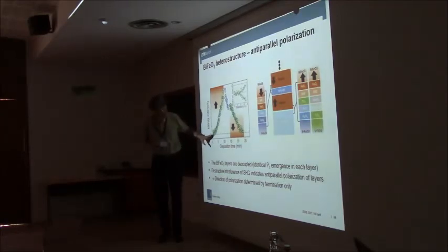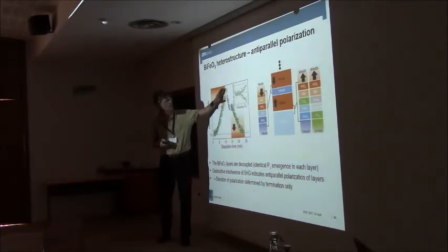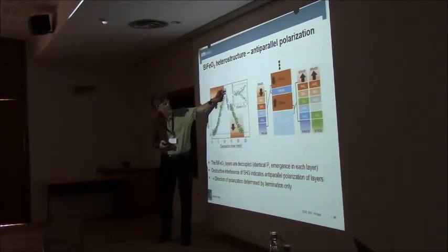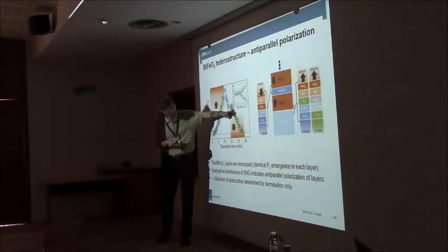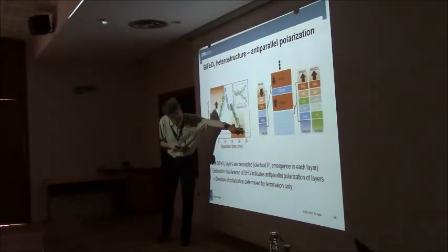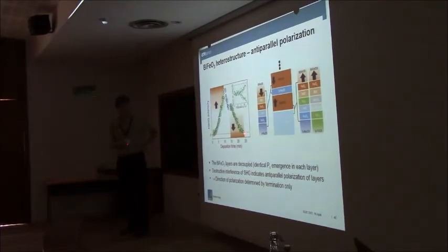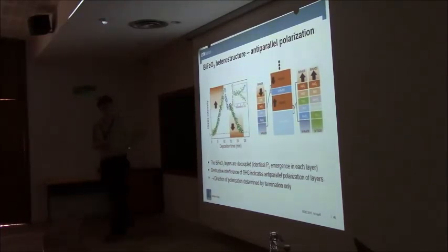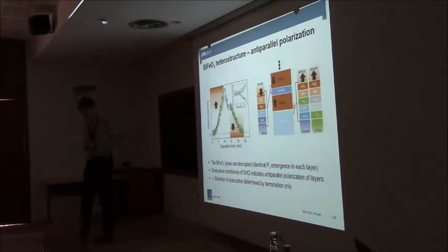You can see it when you track the growth by second harmonic generation. In the first layer you have this continuous increase. Then you grow your metallic interlayer that absorbs a little bit of the light. Then you grow your second, now oppositely polarized layer. You have destructive interference of the two second harmonic contributions, and after a while the two signals compensate. If you just look at this film at this stage, you would say there is no ferroelectricity because there is no SHG. Now you know it's just two ferroelectric layers that compensate in their second harmonic emission, exactly two signals.